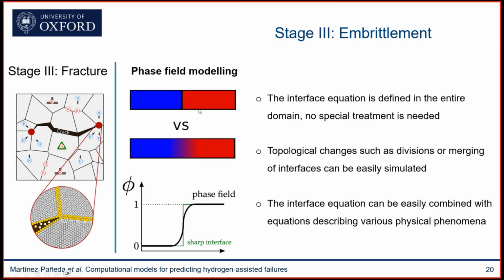Whenever you have two phases, it could be a cracked phase and a solid phase, intact material points, you can treat that interface as discontinuous, or you can smear that interface over a finite domain and use an auxiliary variable, the phase field, to describe where the interface lies. And this implicit treatment of interfaces is computationally very compelling for multiple reasons. One is that the interface equation is defined in the entire domain, so there's no need for any special treatment. The other one is that topological changes such as divisions or merging of interfaces are naturally captured. And a final one that is very convenient here is that the interface equation can be easily combined with equations describing other physical phenomena.